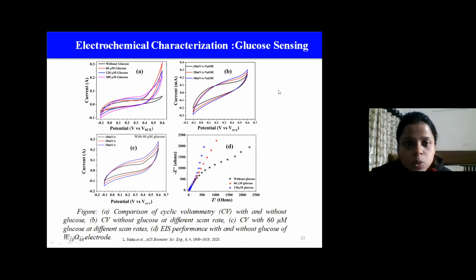This is the glucose sensing application of the same W18O49 nanomaterial. And here we are seeing that in 60 micromolar glucose, the material is giving a huge oxidation peak. And with the increase in the scan rate, there's no shift in the oxidation peak, which gives a stable performance of the nanomaterial.